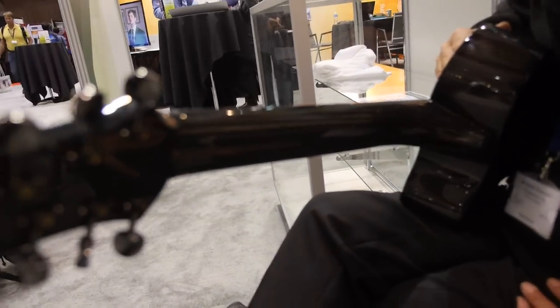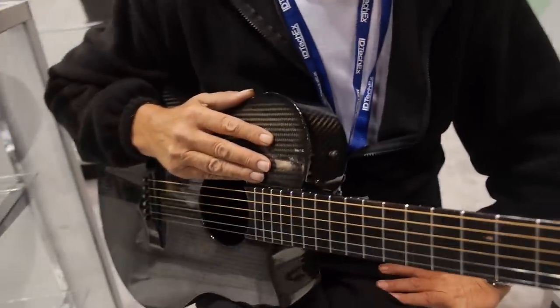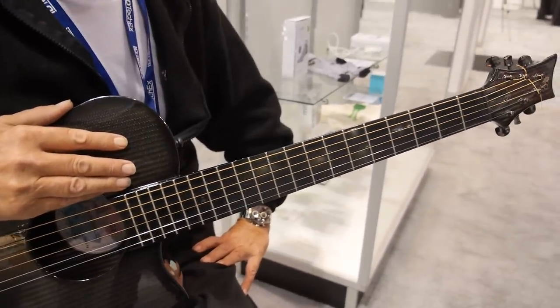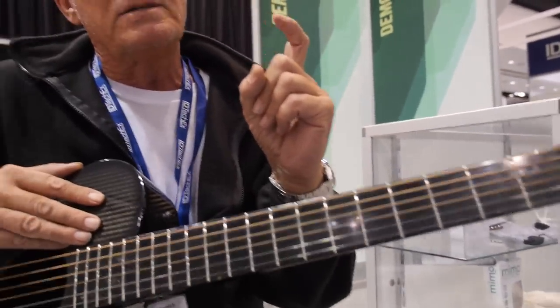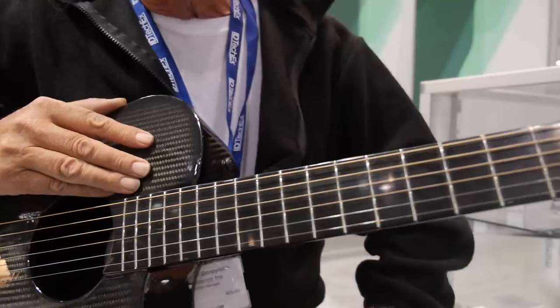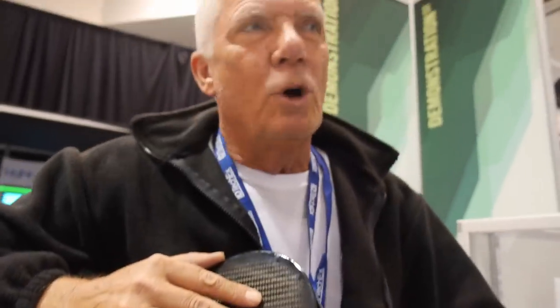This is carbon fiber that they use for racing cars, in aerospace, and in marine. Normally they put epoxy onto it, and it encapsulates the carbon fiber. So the weak spot is the interface between the carbon fiber and the epoxy. By putting it through a dielectric barrier discharge plasma reactor, we put little hooks on the carbon fiber, which are called functionalities. In this case, it's carboxylic or COOH. The hooks then go into loops in the epoxy, so you take the weak spot away. You end up with something that's stronger and lighter than you'd normally get.